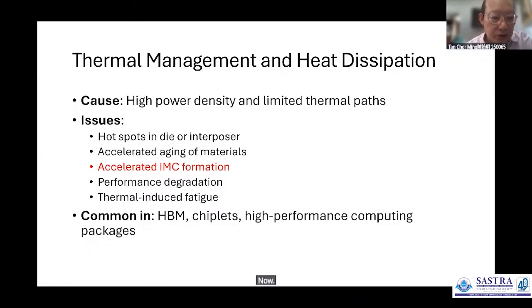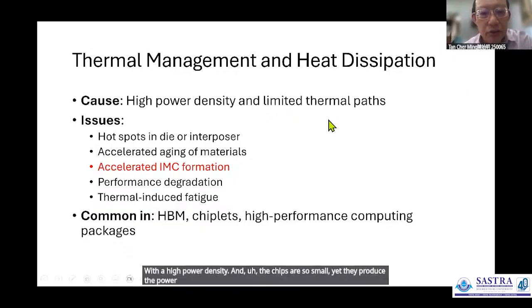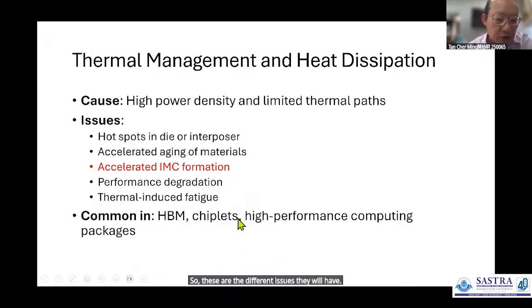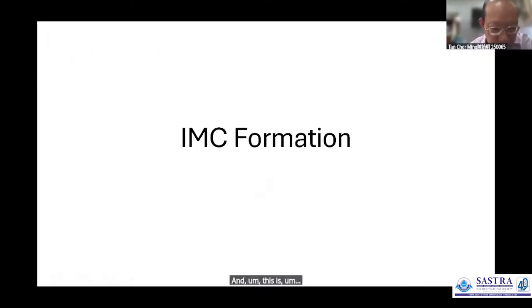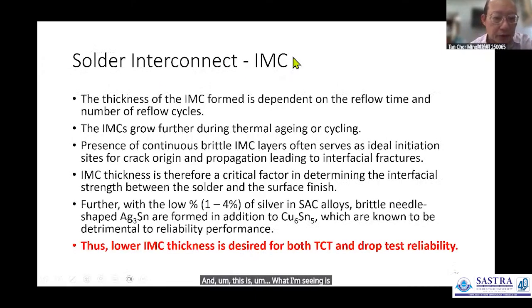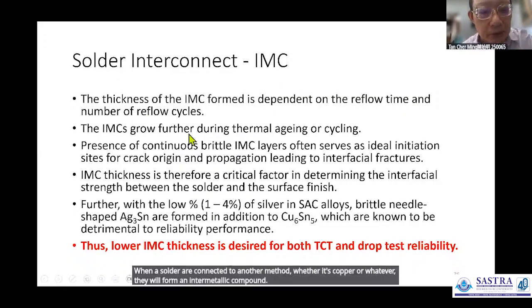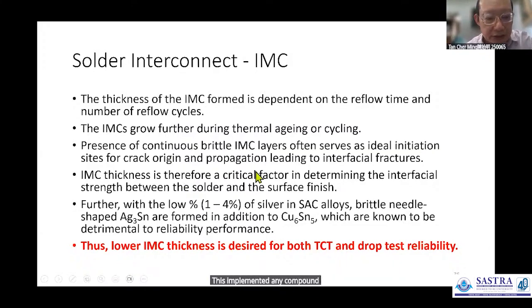Now, thermal management: there are so many chips with a high power density, and the chips are so small, yet they produce the power, so they have limited thermal paths. These are the different issues they will have. One of them is the IMC formation, where IMC is the intermetallic compound. When the solder is connected to another metal, whether it's copper or whatever, they will form an intermetallic compound. This intermetallic compound is necessary to have good soldering. However, when they form, they'll continue to grow.